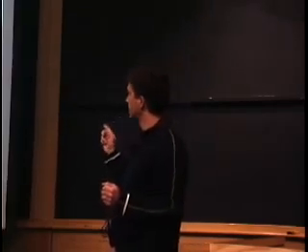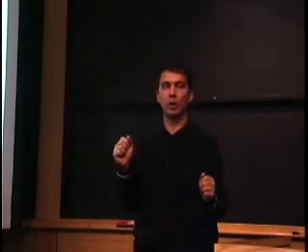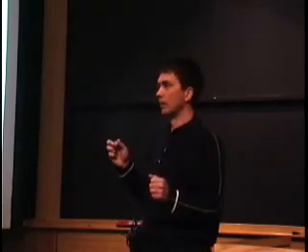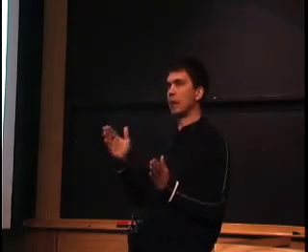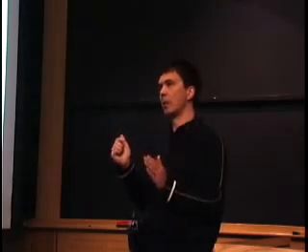Actually, I'm not sure that I know of a single result where LDA gives a lattice parameter that's too big. I've seen that on some occasions in papers, but it's almost always an indication that the people did the calculation wrong. Actually, an LDA lattice parameter that agrees with experiment is usually a wrong calculation. GGA is much more unpredictable. The ones that I've shown here, because they're simple metals and semiconductors, give you a lattice parameter that's too large. In GGA, it's actually also possible to get a lattice parameter that's too small, though it's rare. Most of the time, you're on the higher side. But it's less predictable. And that's sort of slightly problematic with the GGA.